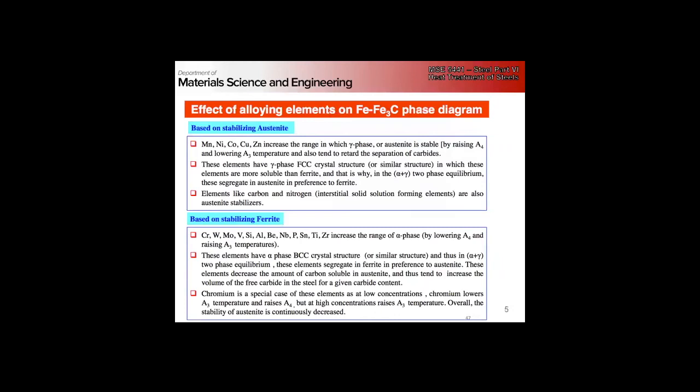As soon as you throw the word weldable in there, all of your other stuff goes out the window. But if we start by thinking about what we can add into steel other than carbon, we can break down alloying elements as either austenite stabilizers or ferrite stabilizers, right? What do the austenite stabilizers all have in common? Generally FCC, right? With the exception of carbon and nitrogen, which are, right, where do they go? They are interstitials.